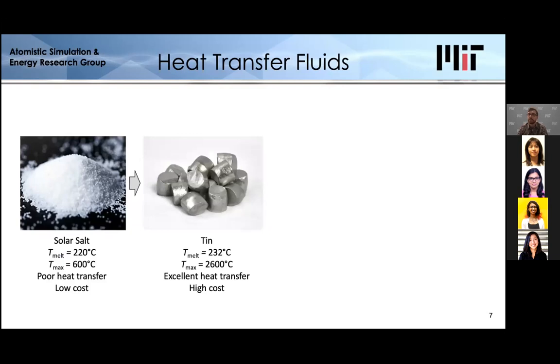So one that we found worked very well was tin. So tin, it's a metal. It has a relatively low melting temperature, right around where solar salt melts. Its boiling temperature is very, very high, so it has a huge range of liquid. It has excellent heat transfer. It has very high thermal conductivity. There's a number of reasons why it's really excellent. Unfortunately, it has high cost, so you get these competing effects.